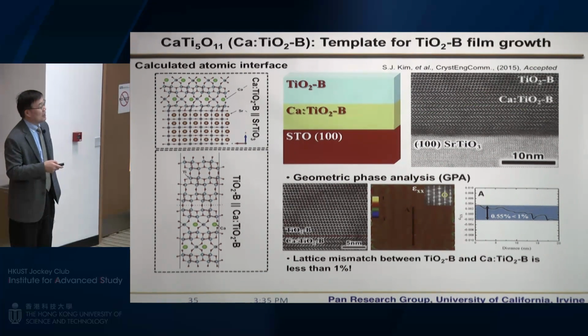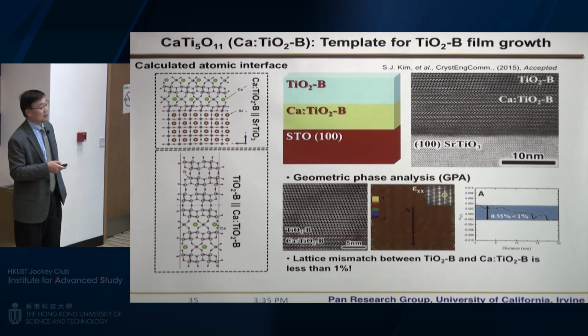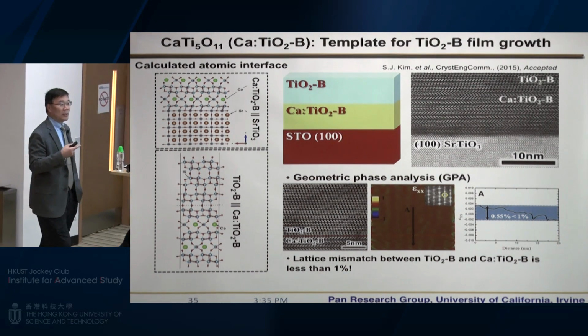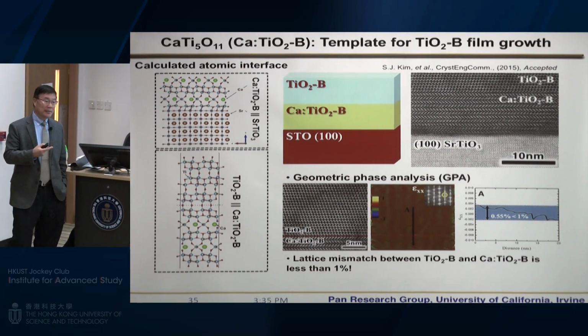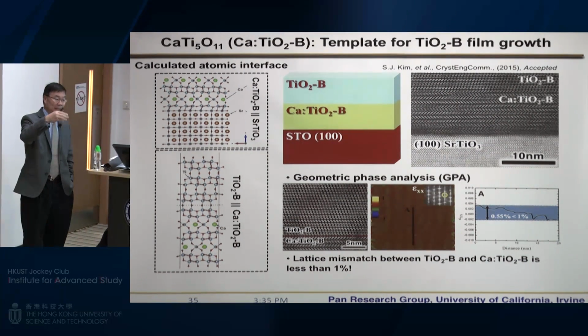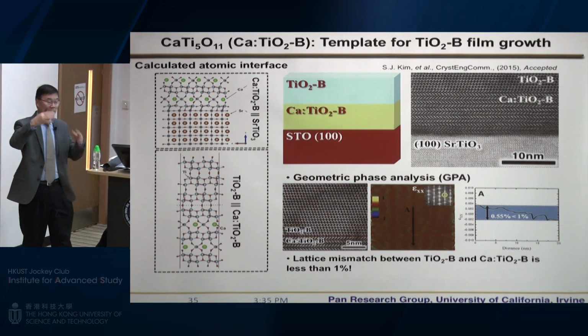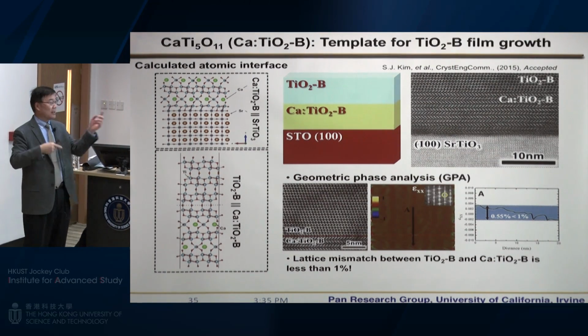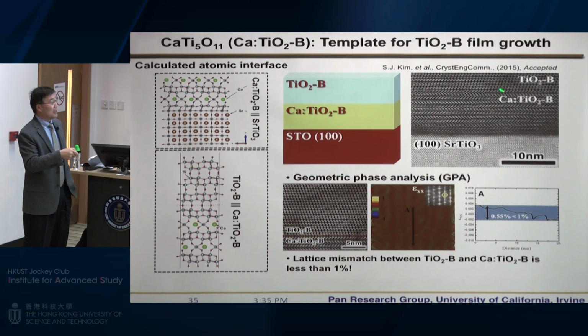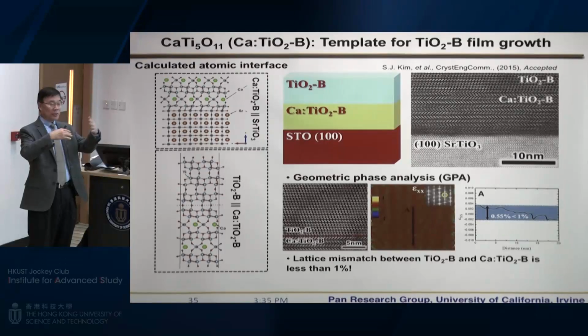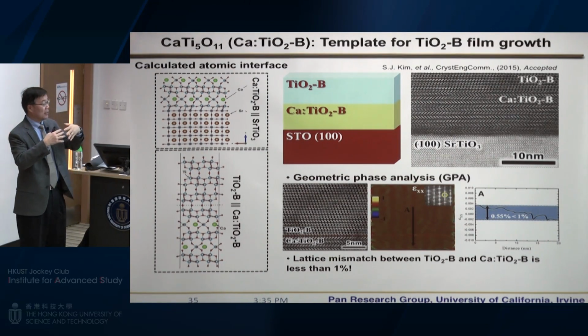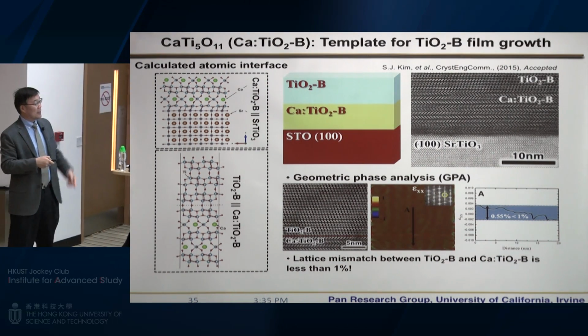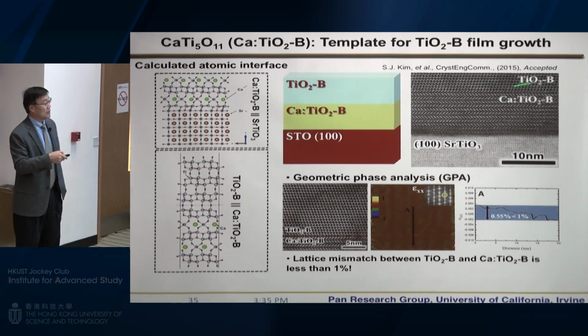So we use pulsed laser deposition to make the bronze phase as a very nice epitaxial film, almost perfect. And we discovered this as a side product of a catalyst study. We studied a so-called intelligent catalyst, a platinum or palladium doped calcium titanate. During the reaction in hydrogen, we saw a small secondary phase of titanium bronze B. Then we figured out there is a structural relationship between this secondary phase and the perfect perovskite. And then we used this as a template to grow epitaxial film.